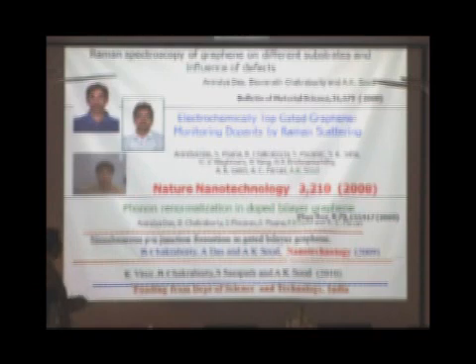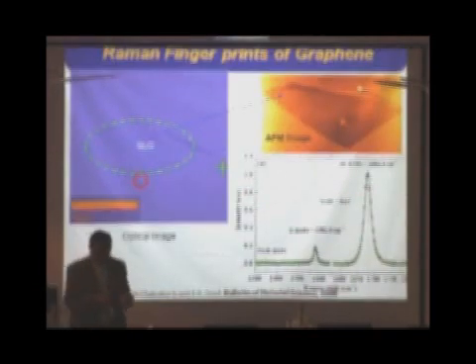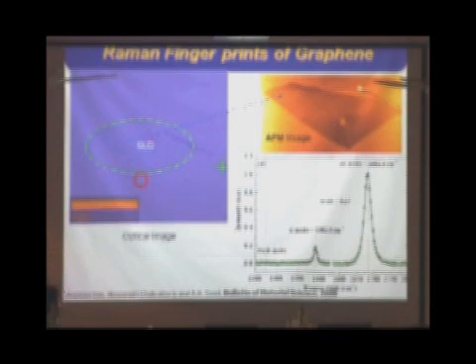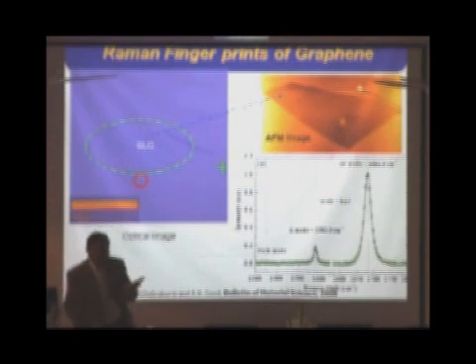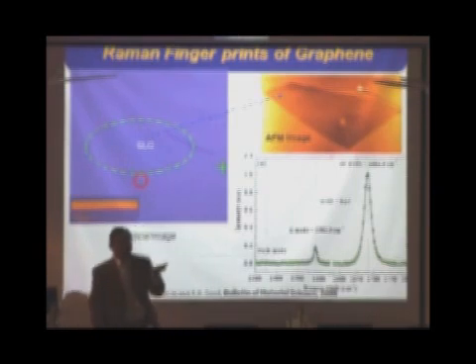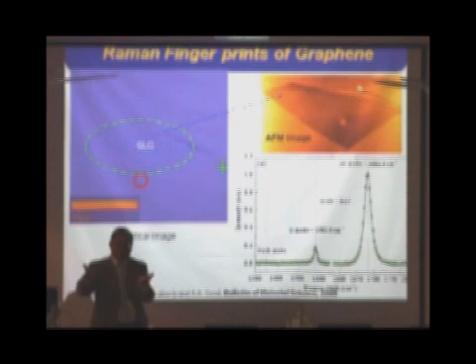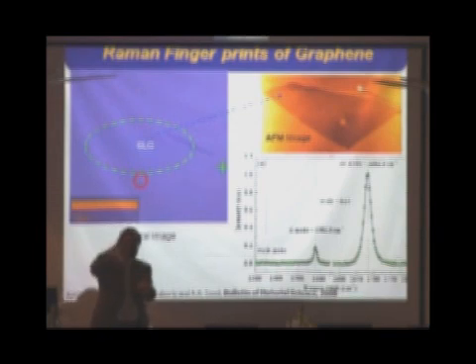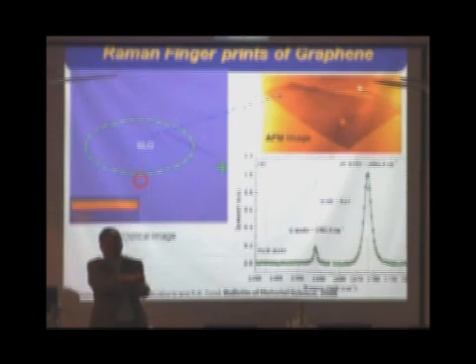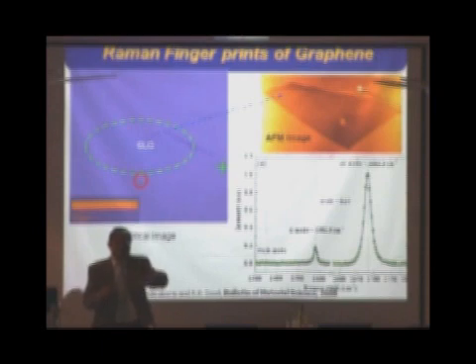When you make graphene and put it on a substrate, you can do AFM and show it is a single layer. The color contrast is very specific if it is a single layer or a bilayer. The simplest fabrication route is scotch tape from your drawer: put it on HOPG, which is a highly oriented graphite, peel it out, and touch the tape on a SiO2 substrate. If you do it correctly and look under a microscope, you will locate many single layers, many bilayers, trilayers and so on. Then you go ahead and make devices.